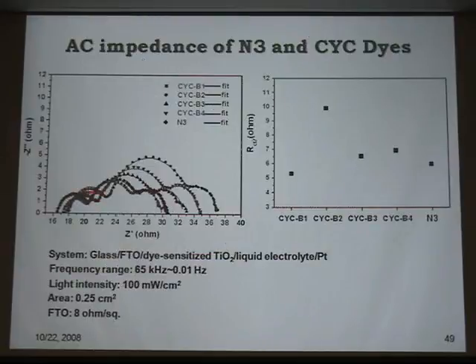In terms of electrochemical measurement, it is the second resistance, which is the charge transfer resistance between electrolyte and titanium dioxide, that will determine the cell performance. So the cell performance of N3 is determined by this charge transfer. So CYCB1 performs the best, which should give you the lowest charge transfer resistance. Here, the resistance is lowest.